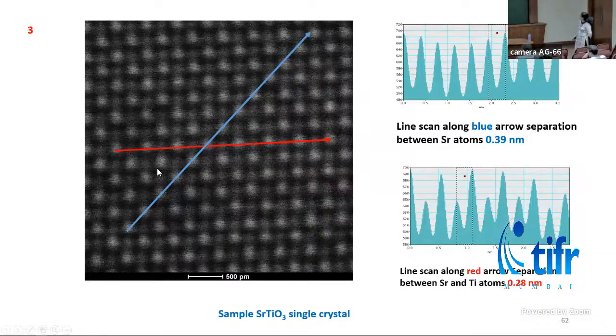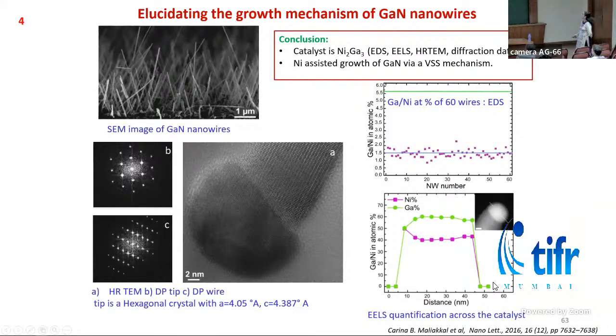The line scan along the blue arrow shows the spacing between strontium atoms, which is 0.39 nanometers, and the line scan along this red line shows the spacing between strontium and titanium atoms, which was about 0.28 nanometers. So this image is from a standard strontium titanate sample. It was taken by Dr. Purandareji.